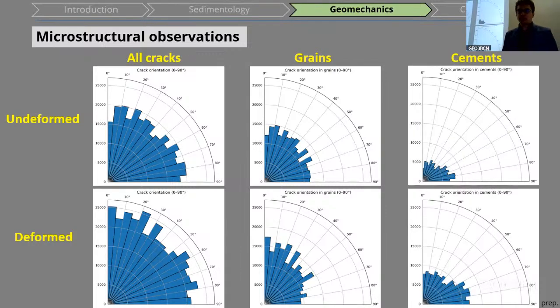And the same is also true for the cement, but you can see there's a clear difference between the cracks in our deformed samples in grains and the cements when it comes to orientation. So that seems to us to indicate that the cements and grains behave differently during the deformation experiments, and that they pick up stress or strain in a different way. We're still trying to map this out, but what we think is that if we have cement right at the boundary between uncemented and cemented layers, this is where we get the highest amount of strain and then also the highest amount of cracks in our cement.